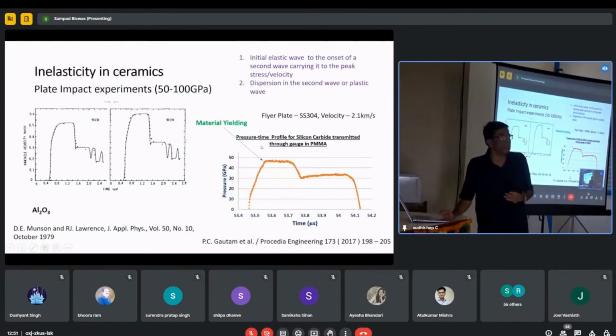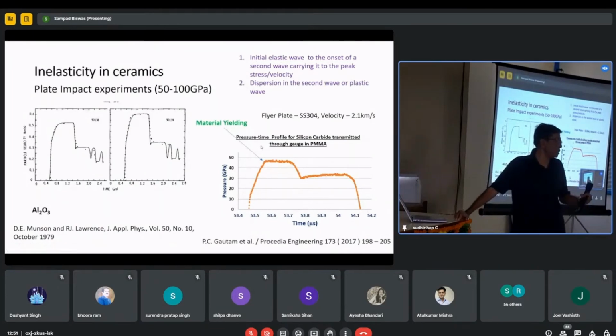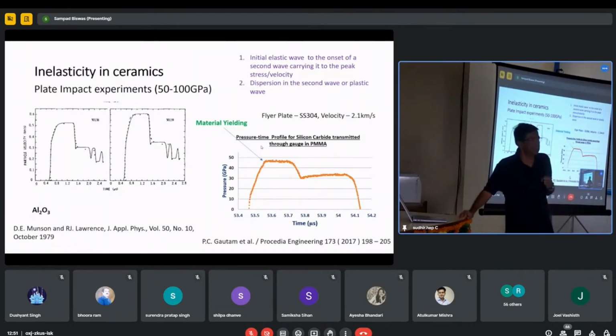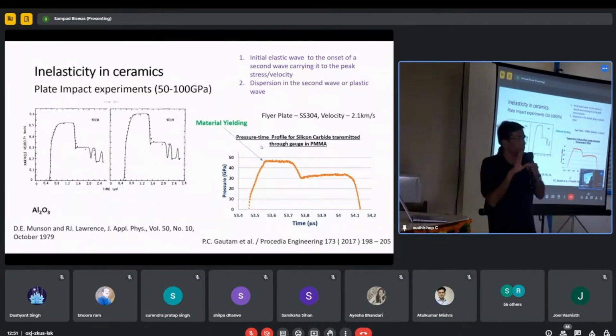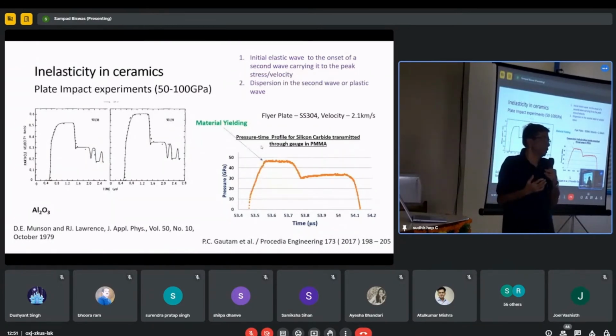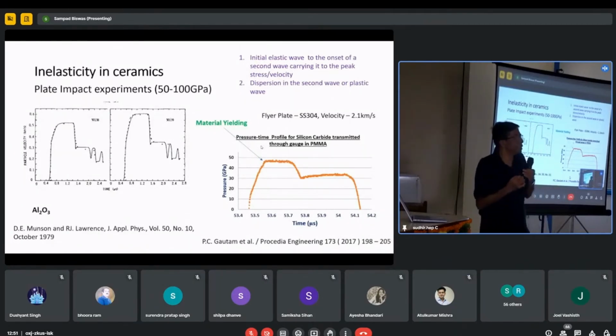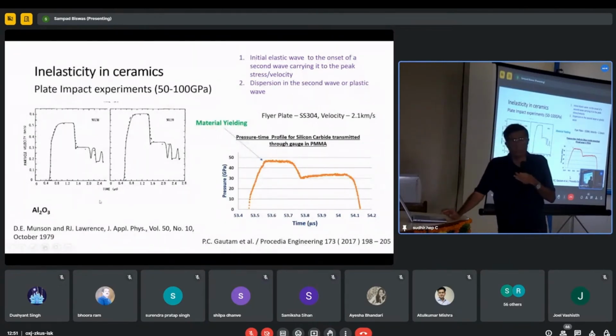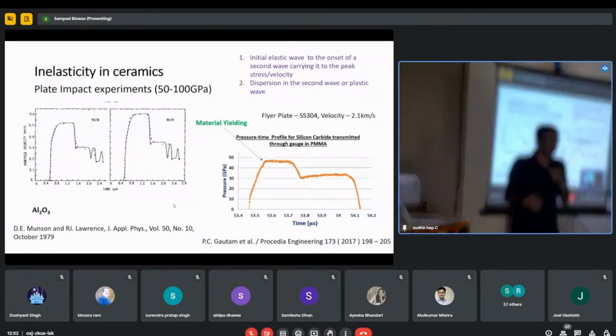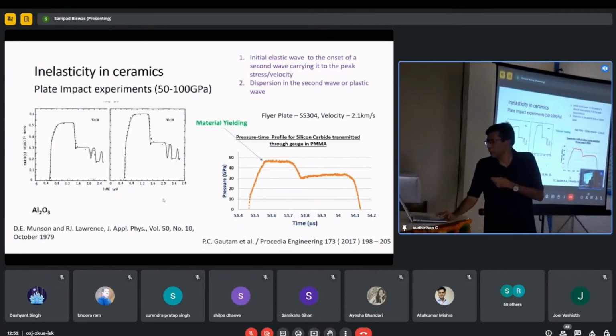Now, the inelasticity of ceramics was first studied by planar shock experiments. Planar shock experiments means you apply a planar wave to the ceramics and then follow the response. These responses are followed by means of a manganin gauge or piezoresistive gauges. You get the particle velocity versus time, and you get a shock Hugoniot also. So Hugoniot characteristics are very important in the case of armor ceramics.